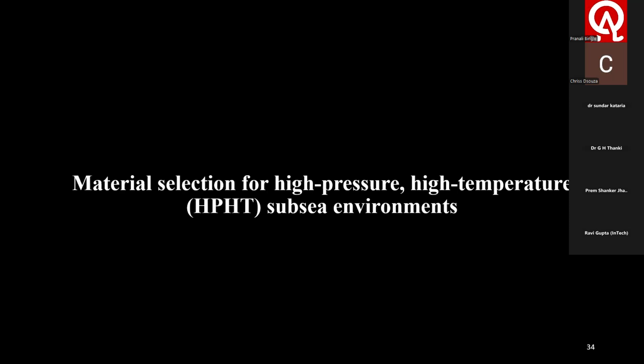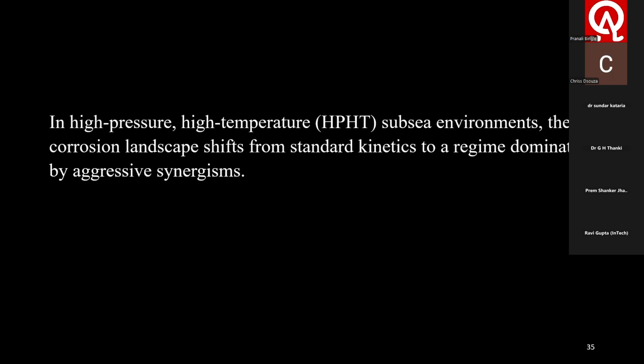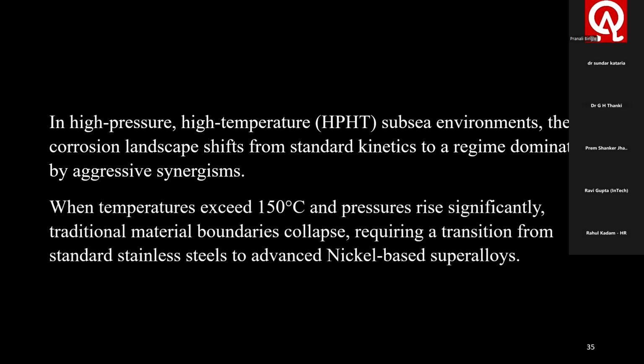Material selection for high pressure, high temperature subsea environments. In high pressure, high temperature subsea environments, the corrosion landscape shifts from standard kinetics to a regime dominated by aggressive synergisms. When temperature exceeds 150 degrees centigrade and pressure rises significantly, traditional material boundaries collapse, requiring a transition from standard stainless steel to advanced nickel-based superalloys.